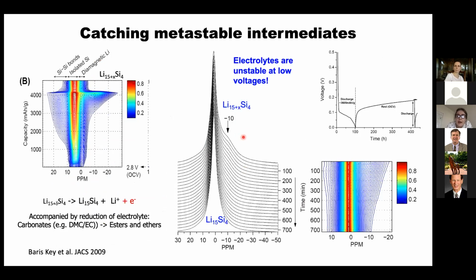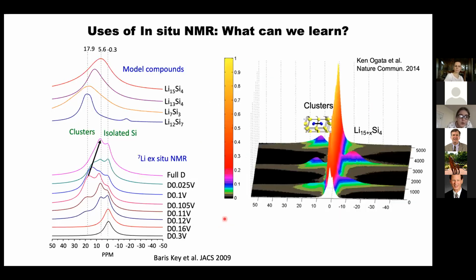When we discharged all the way to low voltages, we stopped and we watched, the open circuit voltage increased and this signal disappeared. And what was happening was that this phase was so reactive, it was reacting with the electrolyte. In itself, it was being oxidized to this phase. And so that meant that when you were looking at things ex situ, as shown in this study here, you couldn't actually capture that phase, but only by doing it in situ could you actually see this phase.